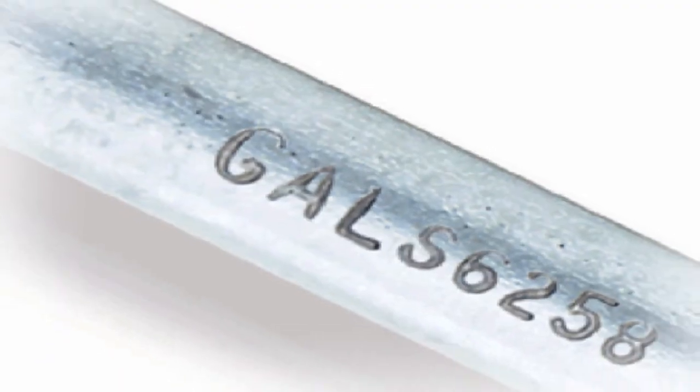Can you tell the thickness of the coating? No. Why does that matter? The NEC requires a minimum of 10 mils of plating on a copper plated rod. The RUS requires 13 mils. ASTM states that for galvanized rods, the zinc coating can't average less than 3.9 mils thick at any point on the rod. I've got no idea.